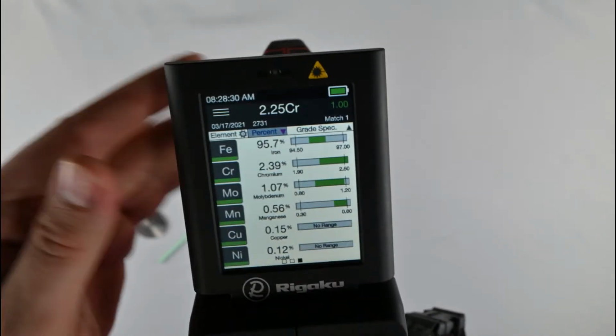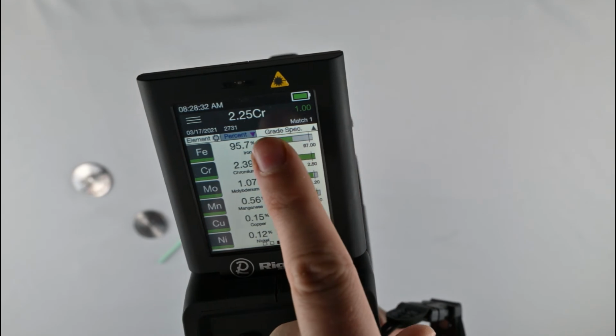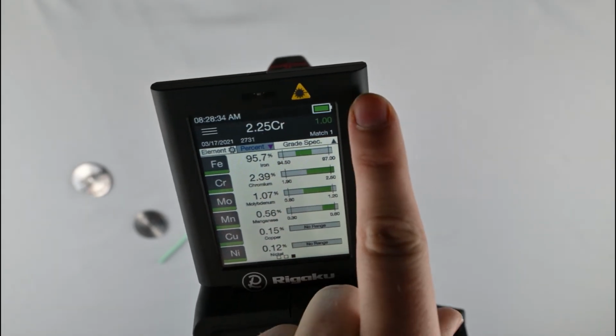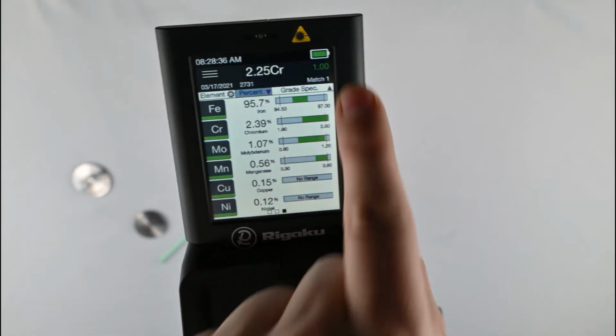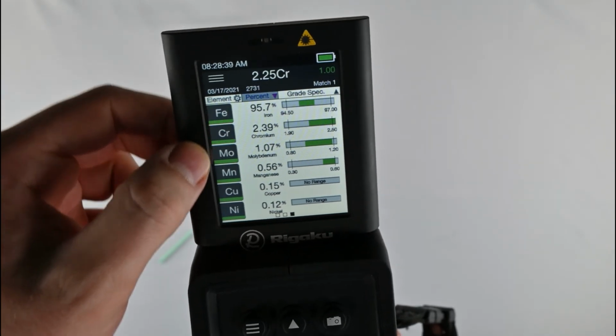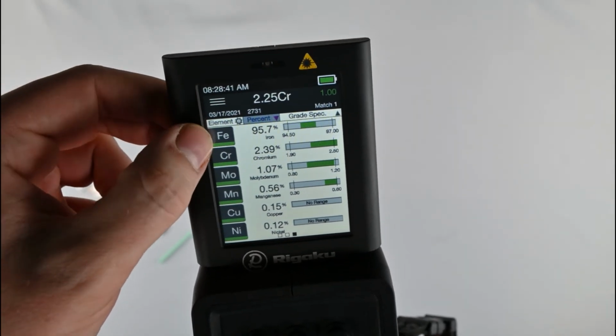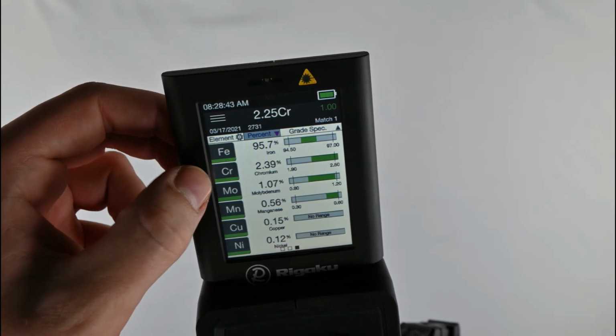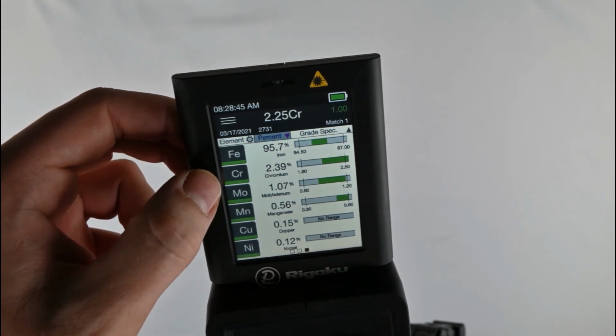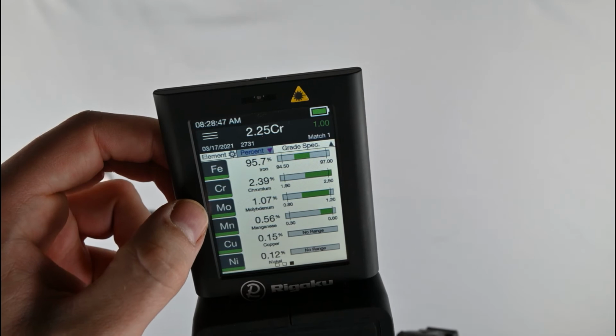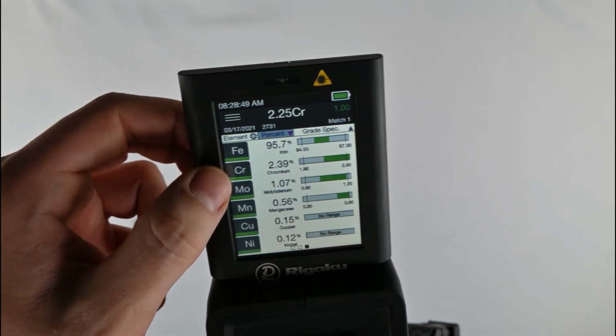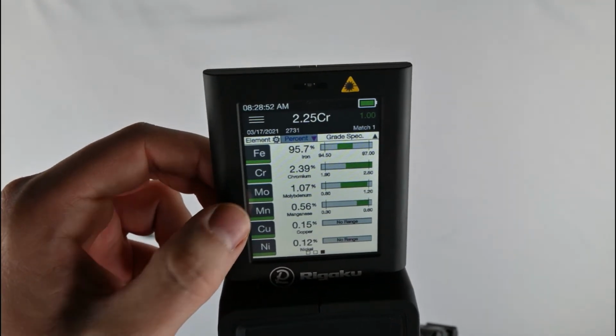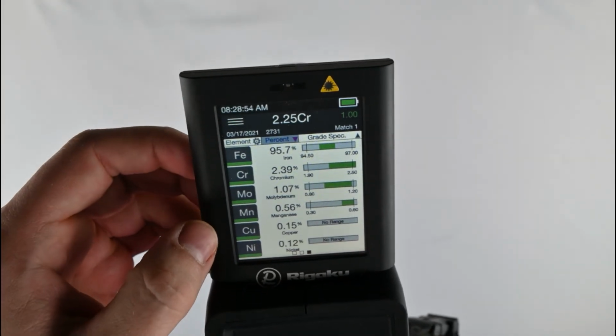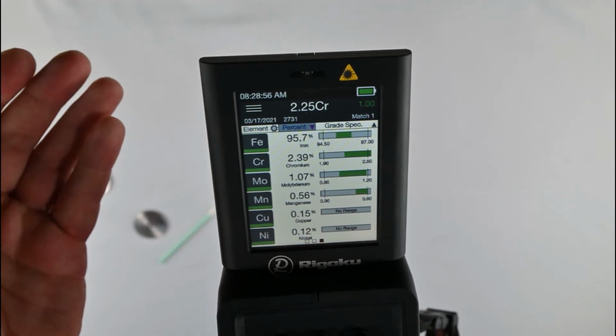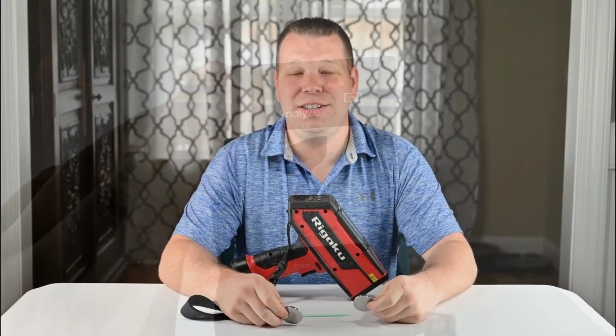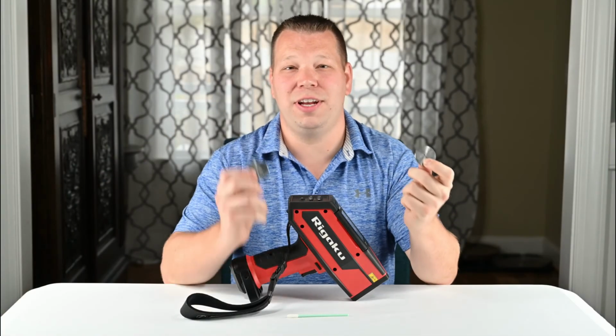Okay, so as you can see, it's pretty easy to see that we call it 2 1/4 chrome, the common name. And up here, we've got 100% match, so it's easy to see with handheld LIBS. The iron is the base element in the material. The chrome here is about 2.4, so pretty high. The moly, excuse me, is right about 1%, so that's where you get that common name. The manganese is about 0.5%, and there are some other contaminant elements in it as well, but it's primarily just a low alloy steel.